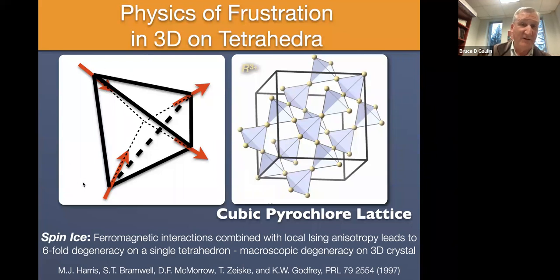But there is still a magnetization associated with any one tetrahedron. And you can see for this one that I've drawn here, it points from left to right, points this way, okay? But the magnetization associated with the tetrahedron is not 4 times the magnetization associated with one of the moments.